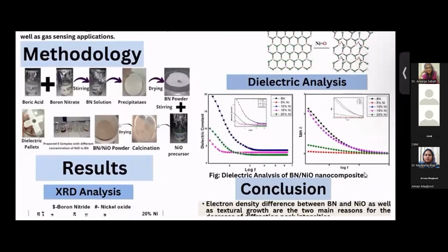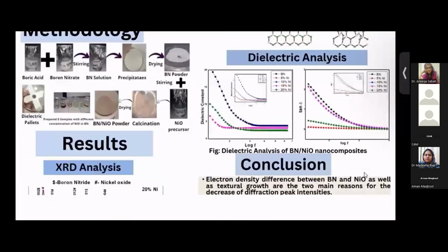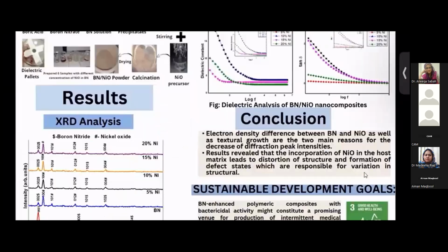Conclusion: electron density differences between boron nitride and nickel oxide, as well as textural growth, are basically the two main reasons for the decrease of diffraction peak intensity. Results revealed that the incorporation of nickel oxide in the host material leads to distortion of the structure and formation of defect states, which are responsible for the variation in structural analysis.